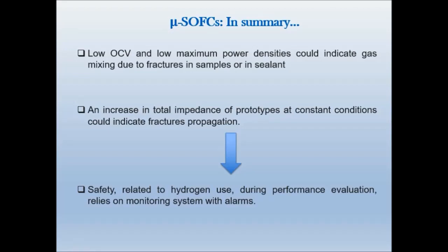Low open circuit voltage and low maximum power density values indicate that hydrogen is mixed with oxygen. An increase of impedance of the samples at constant conditions could indicate propagation of fractures. However, safety related to hydrogen use during performance evaluation of prototypes at a laboratory scale should rely on monitoring systems with alarms.